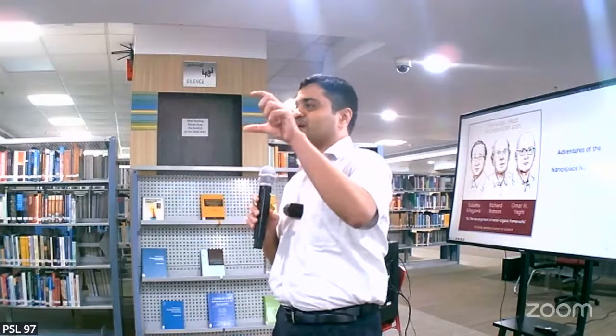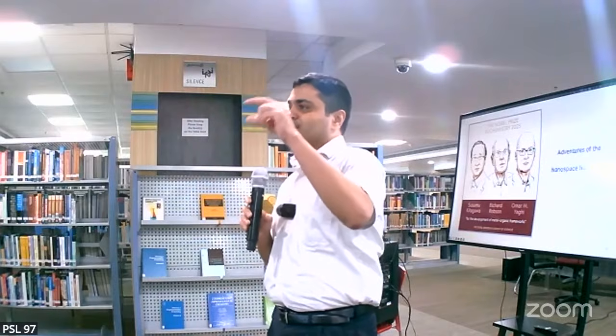But what essentially can happen is you can also use a surface. So, going slightly on a tangent here, recently we worked on one application during COVID, on a face mask: can we have a coating of MOF? And then that particular MOF surface is active, and the surface can be designed in such a way that it interacts with the spike protein of the COVID particles. And essentially, then you're not moving from a small particle to a much bigger particle. So in principle, that is possible, but getting inside the pore is harder because of the size constraints.